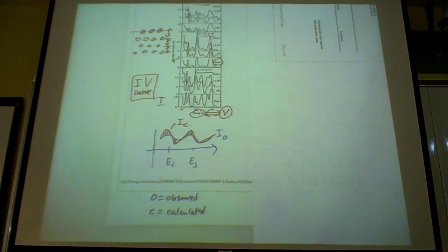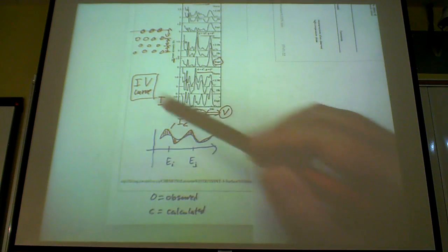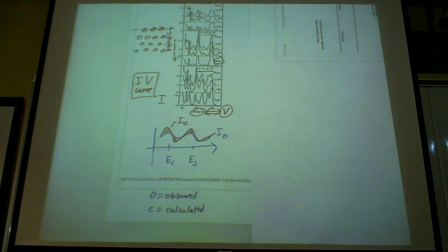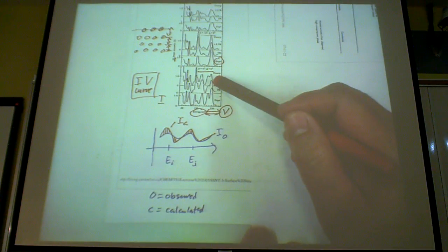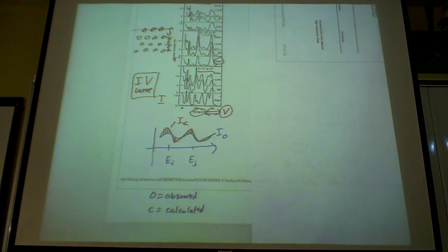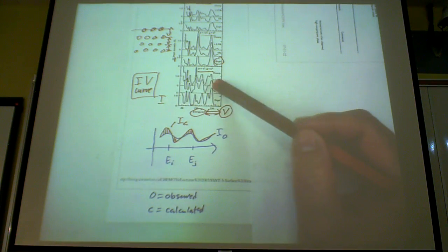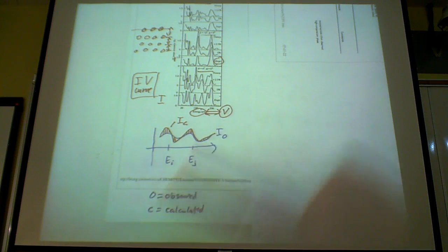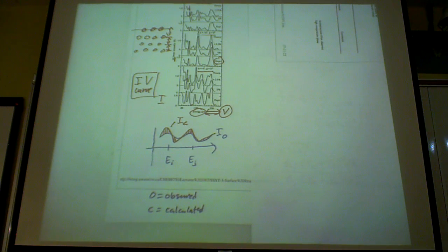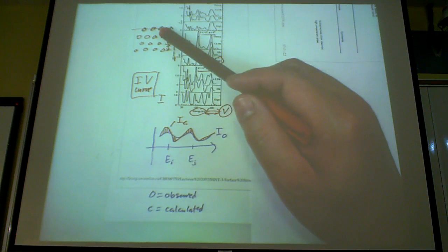And then what do you do? You change the parameter here, change your physical model, and repeat. And then you regenerate this curve again, and you get a different residual, and so forth. So basically you get a different error each time. The differences between theory and experiment is represented by the shaded area. Each time you use a slightly different physical model for a surface, you will get a different error as you go through.